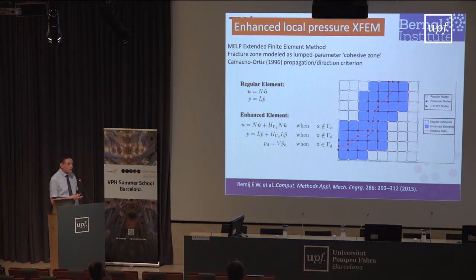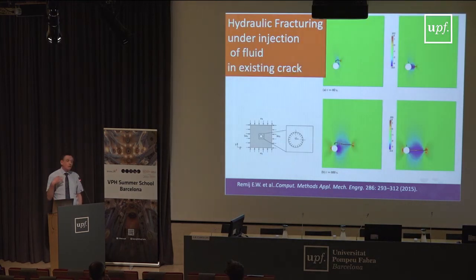We had 3 pressures at each point, because we expect these 3 pressures to be systematically different inside gels. And so we allow fluid to flow from the crack into the formation, into the gel, and from within the gel it is flowing as well because it's a porous medium, and also within the crack it is flowing.